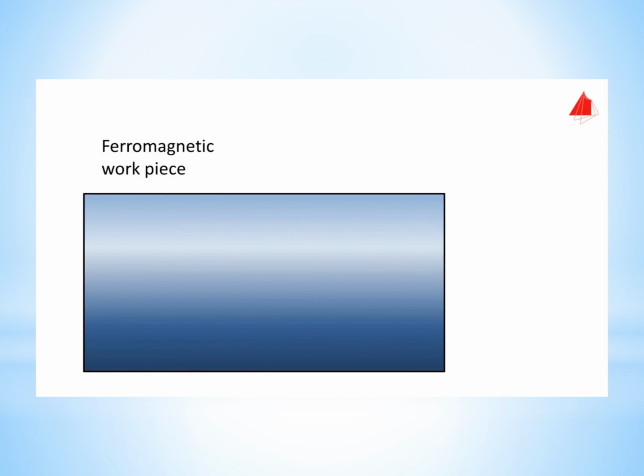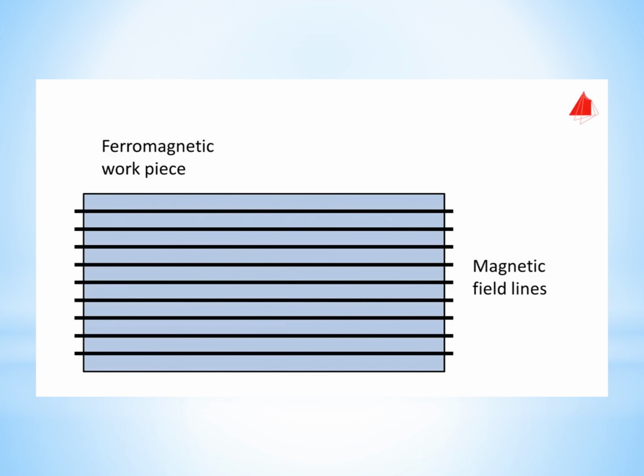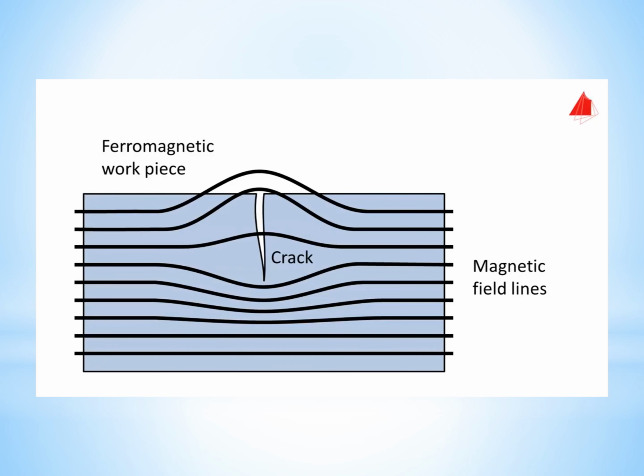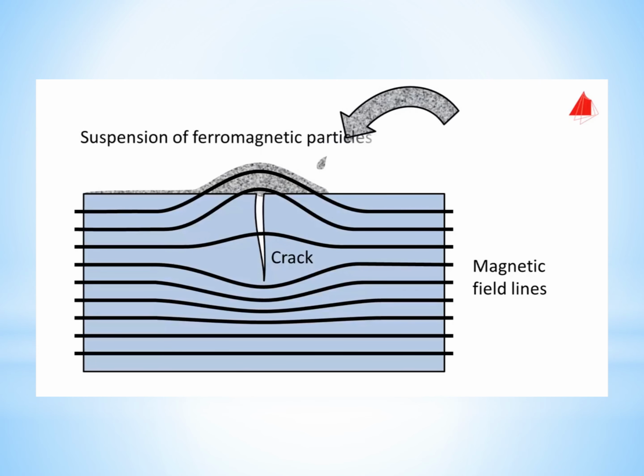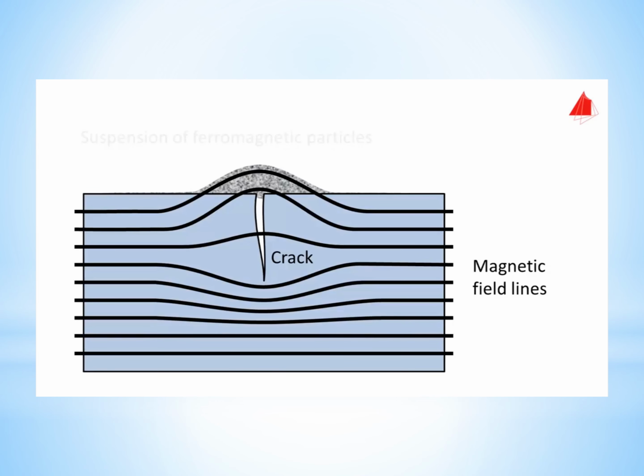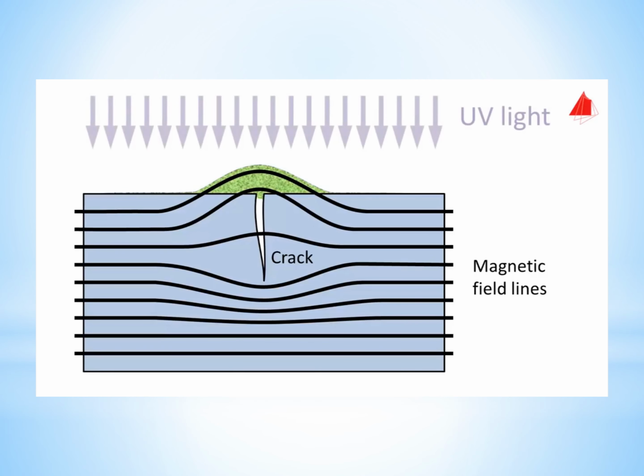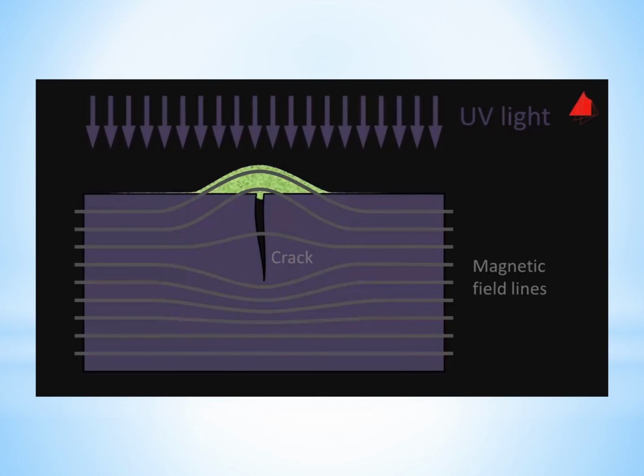The basic principle is to magnetize a ferromagnetic workpiece parallel to its surface, as shown in the sectional view. If the workpiece is free from defects, the magnetic field lines run within the workpiece and parallel to its surface. In places of magnetic inhomogeneity, for instance near cracks, the magnetic field lines will locally leave the surface and a leakage field occurs. Now, if a suspension of ferromagnetic particles is applied onto the test piece surface, the magnetic particles will run off at defect-free areas. In places of leakage fields, the magnetic particles are attracted and clustered together, thus indicating the place of the defect. The method works best using a pigment which covers the magnetic particles and shows fluorescence under ultraviolet light.